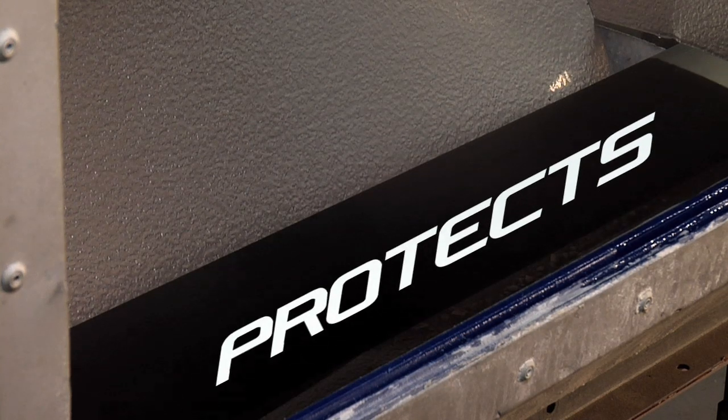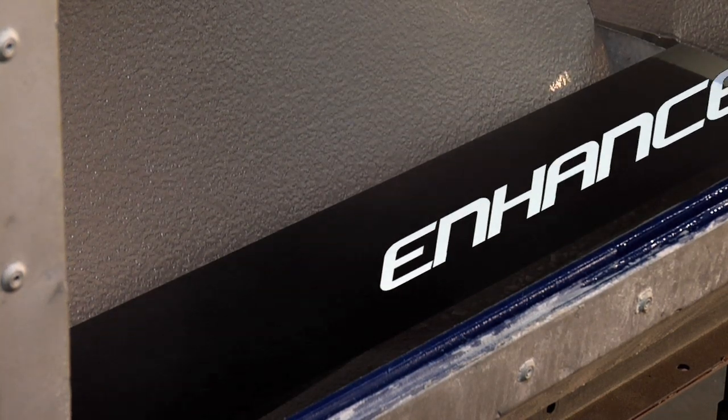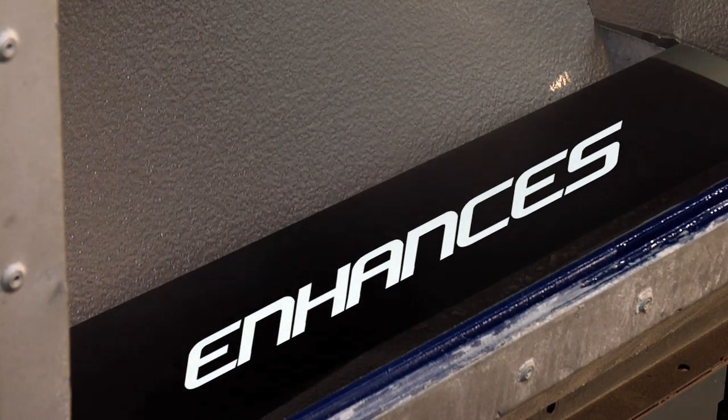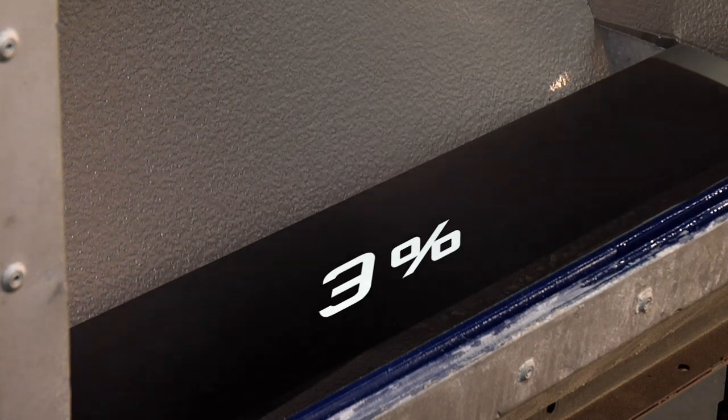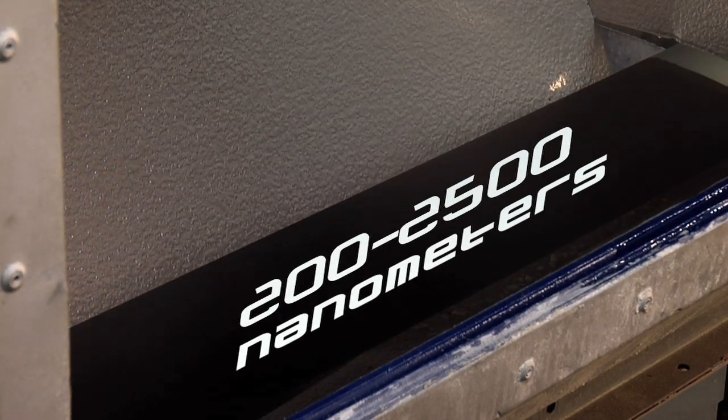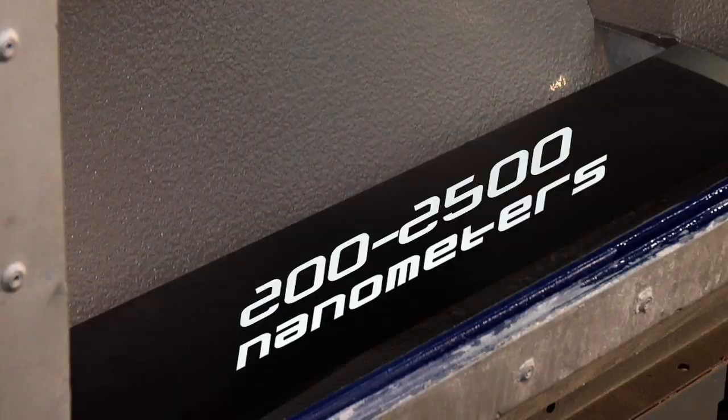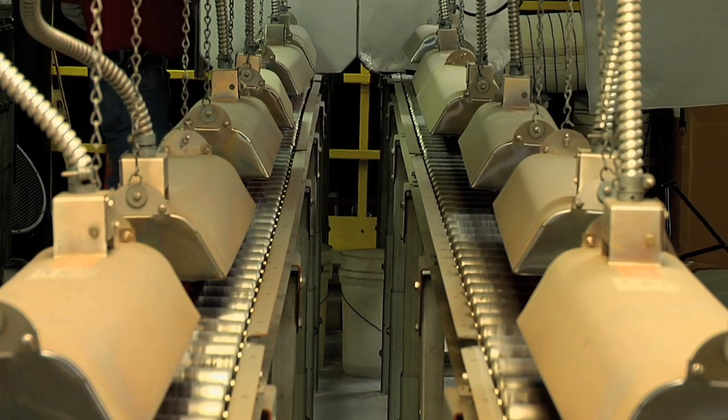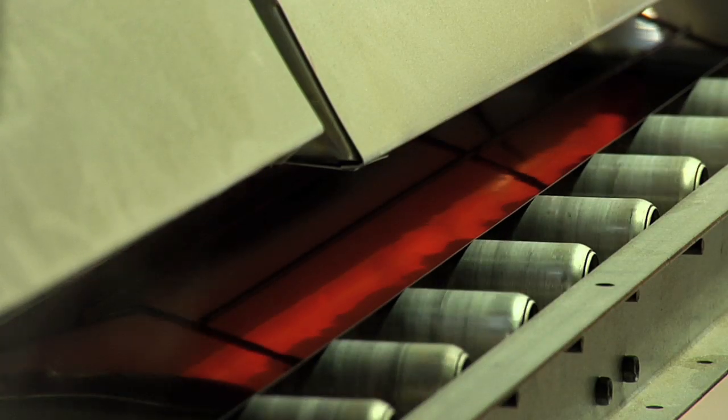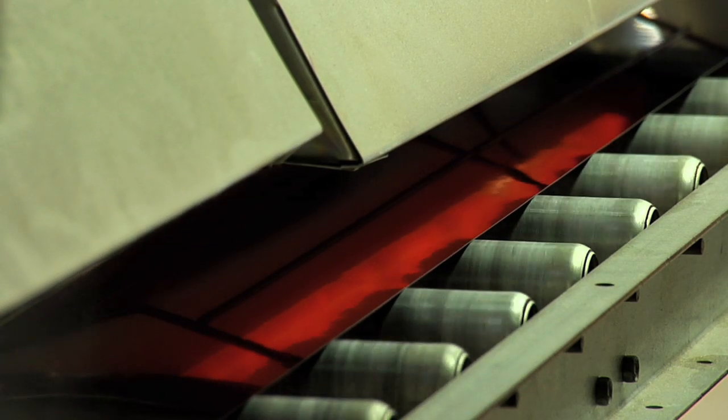This encapsulant protects the selective absorption layer and further enhances the crystal clear absorption performance by as much as 3% over the bandwidth of 200 to 2500 nanometers. The coated copper strip then travels through a series of infrared heaters to dry, densify, and cure the product.